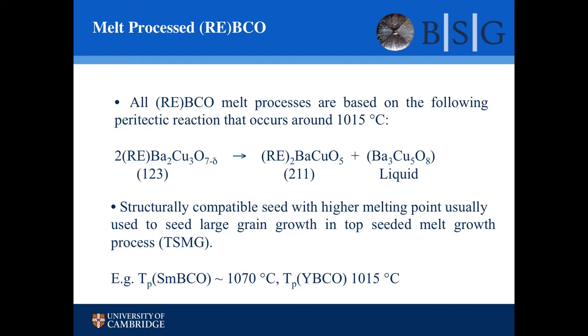You can see this single grain material, these fourfold facet lines tell you it's a single grain, and we've got a seed crystal that we're growing it from at the center. And there's this very convenient peritectic reaction that occurs at about 1,000 degrees C. So our solid, 1, 2, 3, so rare earth 1, barium 2, copper 3, that's the superconducting phase. That breaks down into a second solid phase, non-superconducting, 211, rare earth 2, barium 1, copper 1, and the residual balance of the cations and oxygen forms a liquid phase.